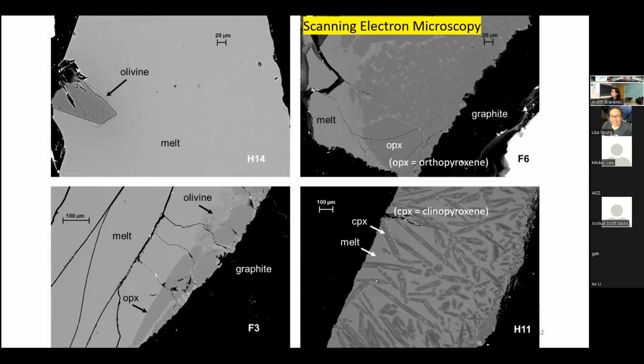Another interesting feature of these experiments is that there was no water initially added to them. They were run entirely anhydrous, because at the time that these papers were published, a dry Martian interior was a favored hypothesis. So water actually wasn't accounted for in these samples. They were supposedly entirely dry.